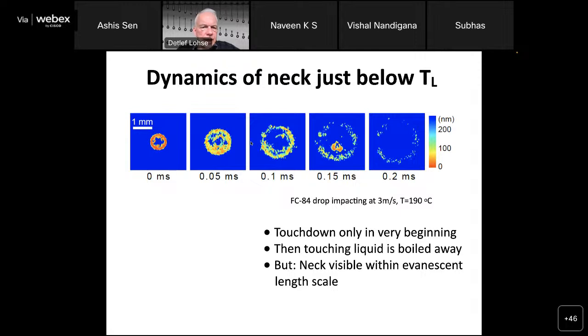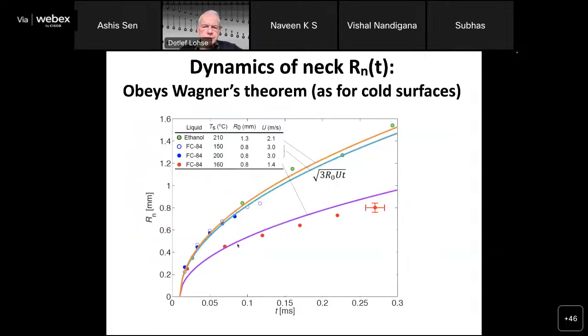Here you see this neck in the middle of the dimple, and you get touch down at the beginning, and when you touch down, this liquid boils away, and this neck is visible thanks to this evanescent length scale. So here you can see the situation. In the middle you have the dimple, and here is the neck, and heat transfer is, of course, in particular here, because here you are closest. Here it's always isolating, and this has quite some bearing on how to model this.